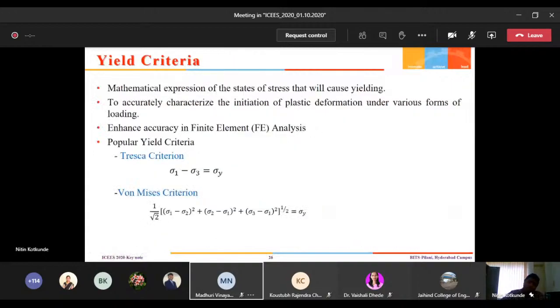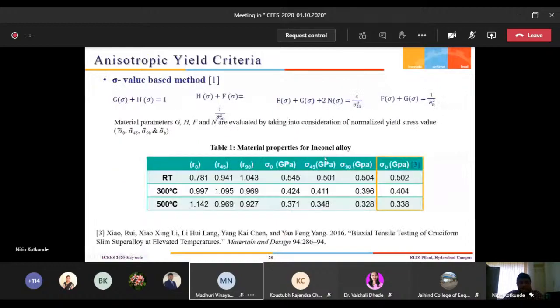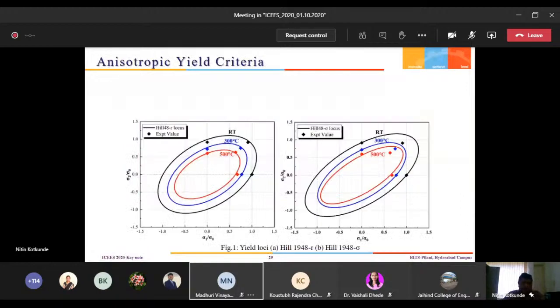Then, as I mentioned, we cannot use the von Mises and Tresca criteria for sheet metal forming applications. It has limitations because isotropy is the condition on which these models have been developed. So we have used anisotropic yield criteria. We considered Hill-based anisotropic yield criteria. These are the equations for that, and these are the constants which we have calculated at the different conditions. I have represented here only 3 cases: room temperature, 300 and 500, and these are the yield locus and the experimental points, which indicate that it predicted the material behavior or the anisotropy very well.